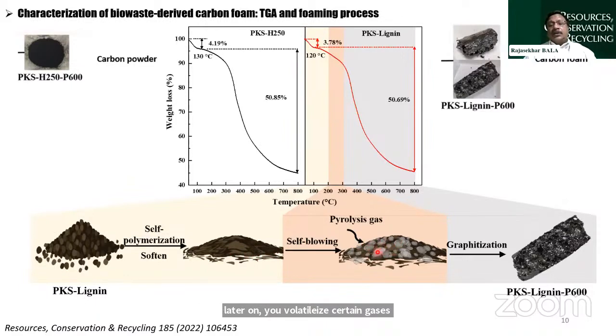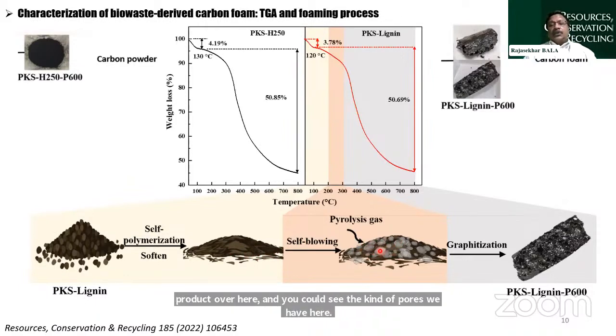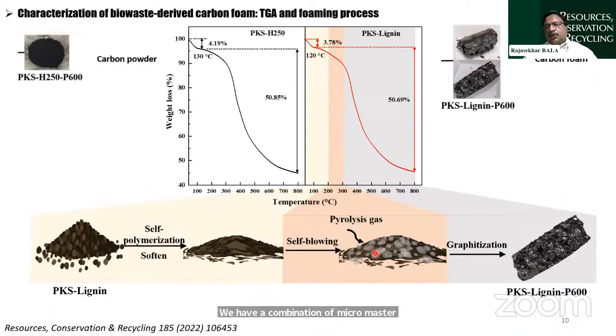We have a combination of micro, meso, and macro pores. These tiny little pores in the product are very important for selectively capturing CO2 and concentrating it onto the material of choice. And eventually, when you do the pyrolysis through graphitization, you get the carbon foam that we have here. This is what I call the feedstock, lignin, processed at a temperature of 600 degrees Celsius through pyrolysis.